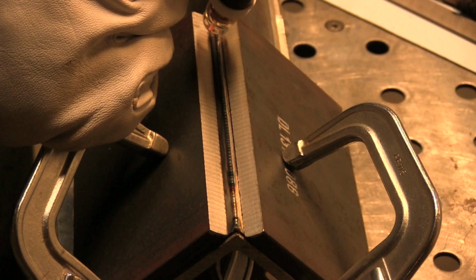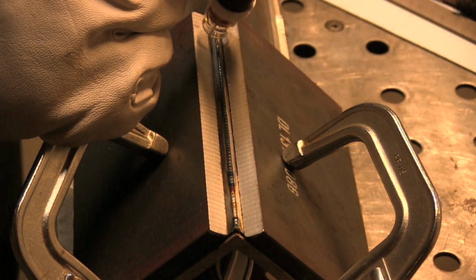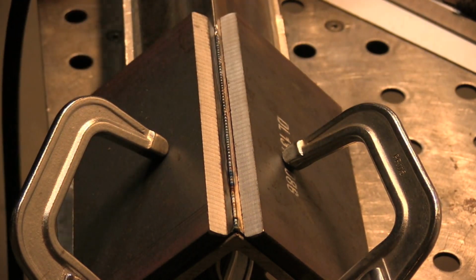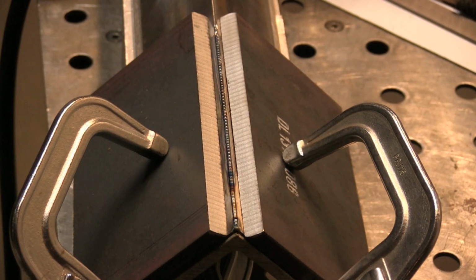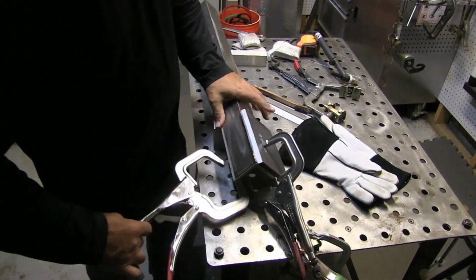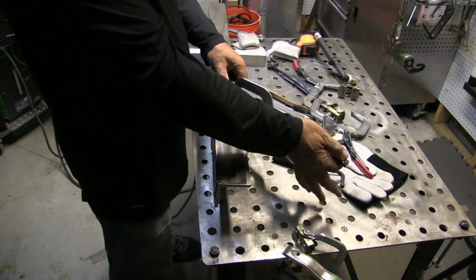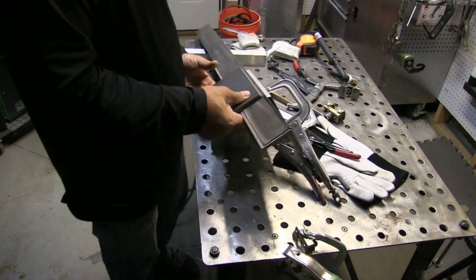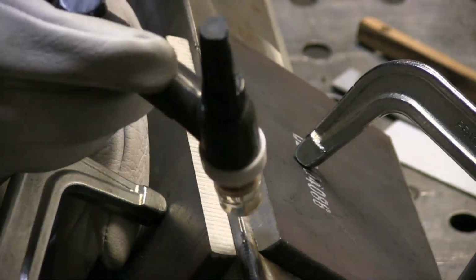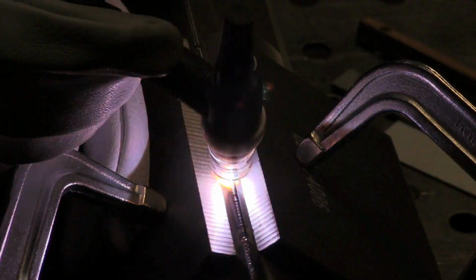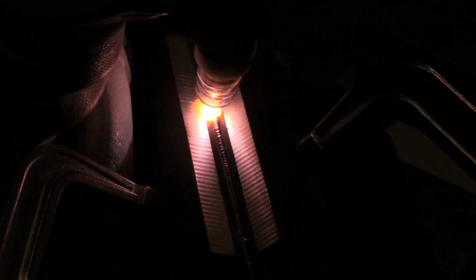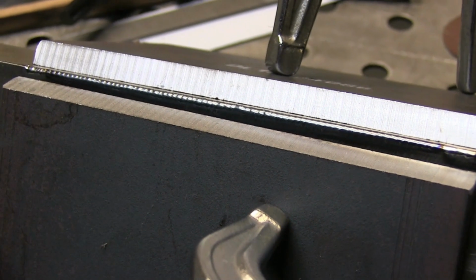And this works pretty well, I gotta admit. It would probably work a little bit better if I had aluminum drawing out the heat, but it's pulling a lot of heat out here. There's some very slight discoloration. The only issue is you just have to keep moving the chill bars. You can only run within the chill bars. But it's worth it. It really, really limits heat input. It really, really limits distortion.